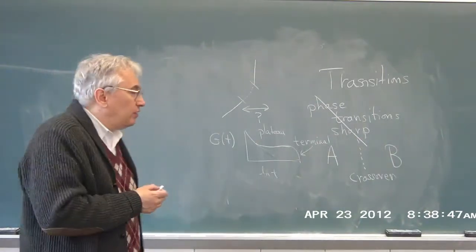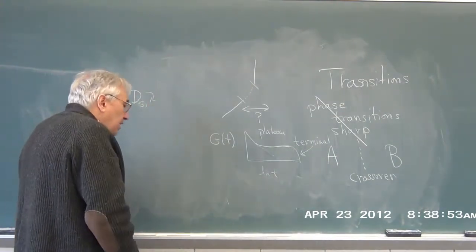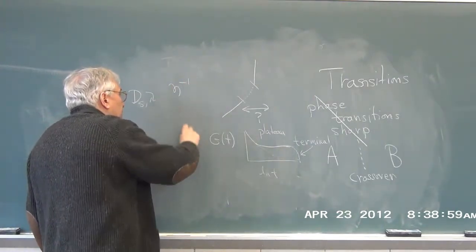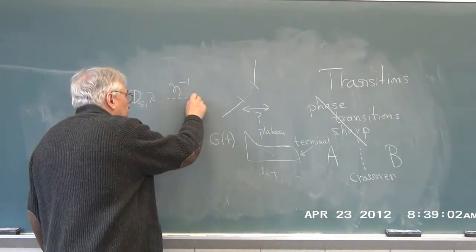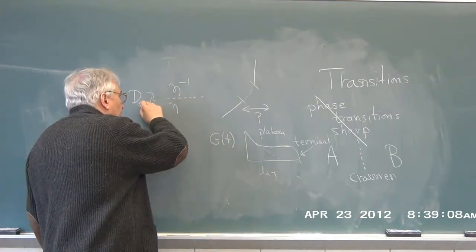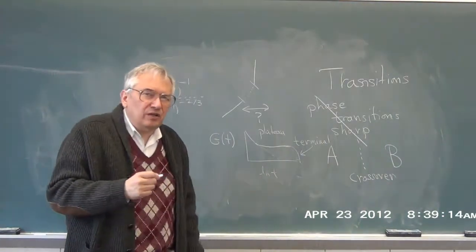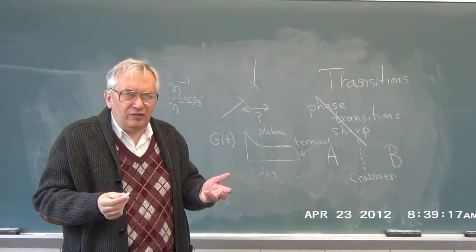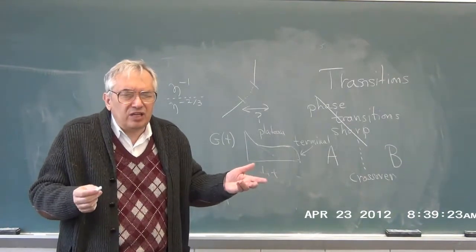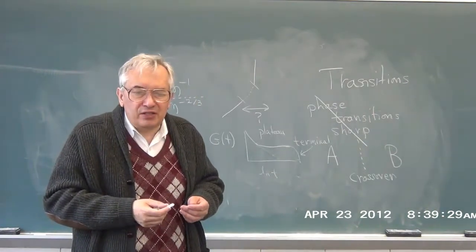Okay. So did we actually see transitions? Well, yes, we saw several of them. For example, for small molecule diffusion or conductivity, I was able to point out that if we look at these as a function of viscosity, we see something that depends as eta to the minus 1, this is in the literature, up to some boundary, and above that we see the diffusion coefficient going as eta to the minus 2/3 or so. And that transition, well, it's clearly going to depend on what the solvent is. But in the aqueous systems that were looked at, it was someplace near 5 centipoise. And that's meant to be a somewhat imprecise statement.